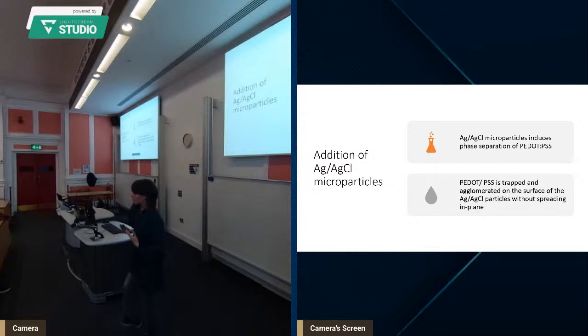So another way to improve the signal of the EEG is by adding silver and silver chloride particles. What silver chloride microparticles do is help the agglomeration of PEDOT PSS. We want these agglomerates within the elastomer. We can add silver chloride to reduce the size of these agglomerates, but also increase the number of these agglomerates. This helps the stretchability of the material because there's more space covered by the elastomer, but it also increases the conductivity of the material because it increases the number of agglomerates, while reducing their size. So the signal is better read by the electrode.